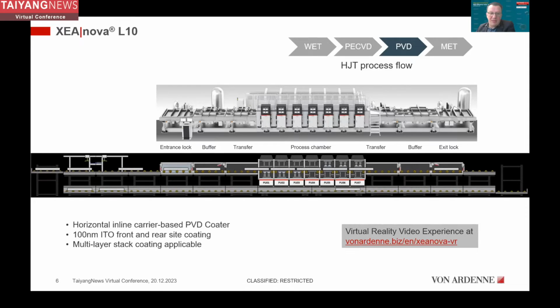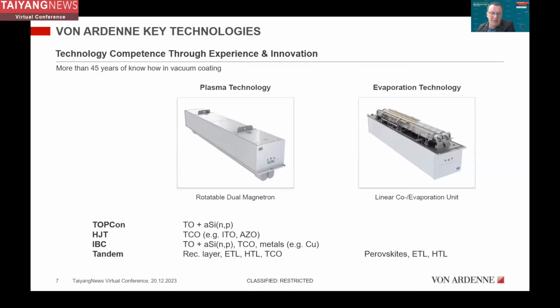So that's basically always the same principle. For sure, we apply different technologies for the different customer needs. For TOPCon, heterojunction, and IBC, we apply rotatable dual magnetron technology, where we apply the tunnel oxide and the doped silicon for TOPCon, either N or P type. For heterojunction, we apply TCO coatings, for example, ITO or AZO. And for the IBC structures based on TOPCon, you use the same as before as a tunnel oxide and the doped silicon, or you can use for heterojunction-based back contact cells a TCO, or at the end also metals for doing seed layer coating for the plating technology.